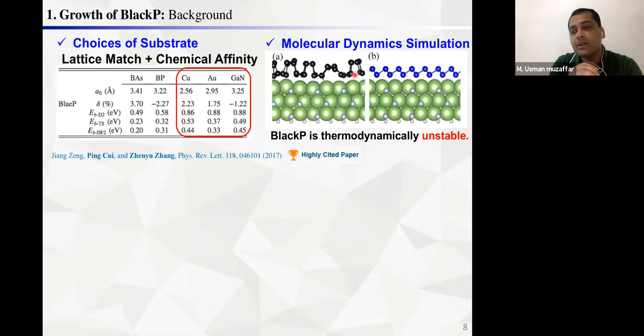And then we recorded the total free energy of the system. We find that within the temperature environment, blue phosphorene can be readily stabilized on the gallium nitride substrate. You can see that after 50 picoseconds, the blue phosphorene system has a very ordered structure. But when we put black phosphorene on gallium nitride, a distortion appeared. It means that in the temperature environment, this system is not as stable, so it is not as suitable.